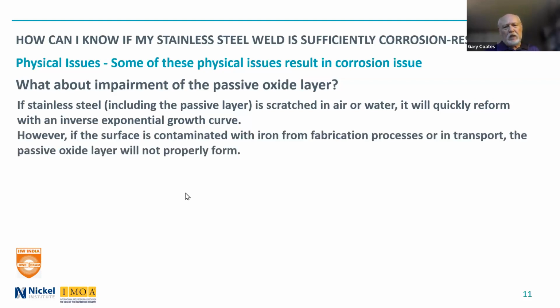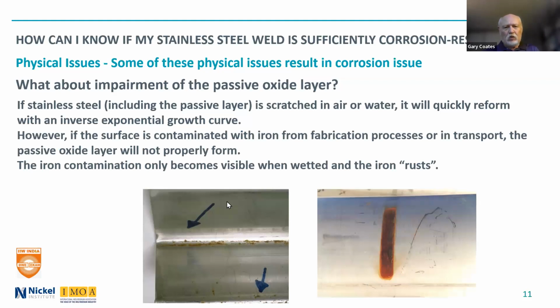Now, if the surface is contaminated with iron during a fabrication process or in transport, the passive oxide layer will not properly form because it has iron on the surface. And this iron contamination only becomes visible when it is wetted and the iron actually rusts. Prior to that point, it's really in the metallic form, and it looks for the most part like stainless steel, but you might get a feeling that, okay, you see a scratch or something where there could be iron. And so only when it is wetted and the iron rusts, you get iron oxide, and that is highly visible.